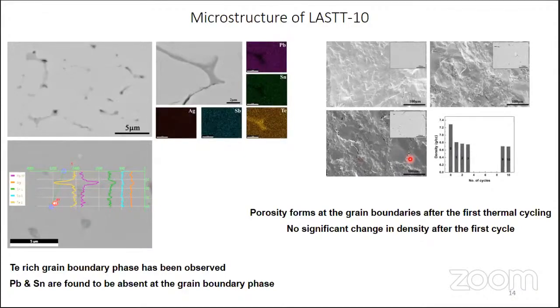We can't say whether it vaporized or sublimated, or whether it melted and infiltrated into the matrix. Something metallurgically happened, but at the end of this 10 cycles, or the end of several cycles, the initial microstructure is not retained. It is changing into this, and that is why we ended up with a difference in thermal conductivity, because porosity will influence the thermal conductivity as well as the electrical conductivity. So even though this material in the literature shows very impressive ZT, it is not the correct way to prepare it and claim something. You have to anneal it for a long duration until you get a stable microstructure and a stable chemistry. Then what performance it shows is very critical.